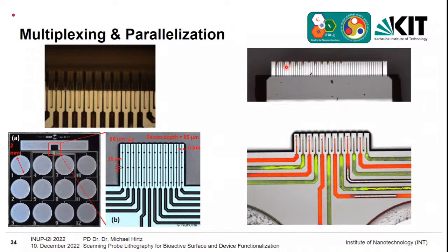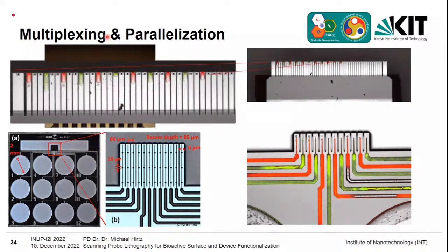By this, the tip array itself can carry, for example, different inks on different tips. So this has happened here. Here you see an inkwell, and you see there are 2 different kinds of fluorescent inks. And here each 4th tip was covered by putting it in here. It's actually the array that you can also see here. So each 4th is getting into a microchannel, and you can see that they can now carry different inks. And this means that you can write in parallel. The black thing here is a pyramidal tip. And in parallel, you can write these different inks next to each other.